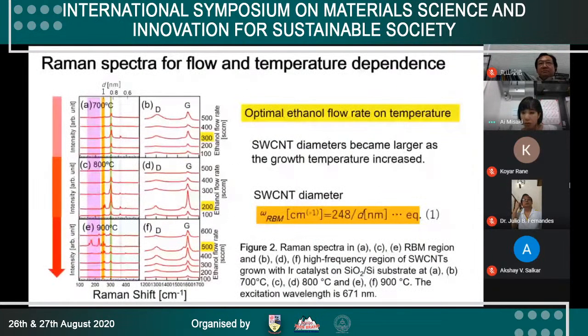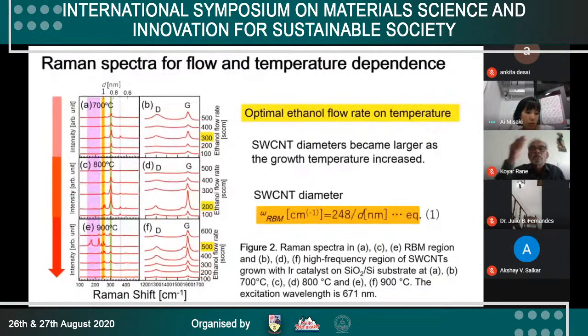Moving on to the next slide: Raman spectra for flow and thermal dependence. Figure 2 shows Raman spectra of the samples grown at 700 to 900 degrees C and an ethanol flow rate of 100 to 500 SCCM for 10 minutes. Single-walled carbon nanotubes were grown from an iridium catalyst. At 700 degrees C, an ethanol flow rate of 300 SCCM is optimum.